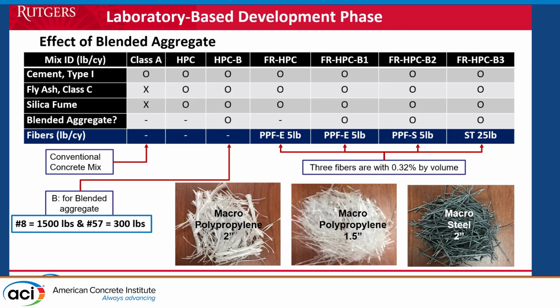During our lab work, we discovered that when we blend the aggregate, before we even started using the fibers, there was very good performance in the mix, meaning that the shrinkage was reduced and there were better results for the rapid chloride permeability. So we ended up requiring blended aggregate. Some of the concrete producers already blend their aggregate, so they already have compartments. You can see this blended here, HPCB. Whatever has a B at the end is a blended aggregate.